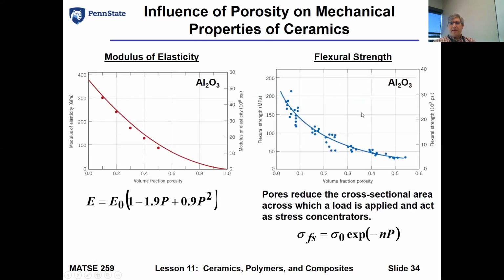So that leads us back into why do they fail? This flexural strength is going to vary, and it goes back to that processing. We talked about process structure properties a lot leading up to this throughout the course. But in this case, the process structure properties really come back to porosity and these pores. What they do is they reduce that cross-sectional area. They lead to stress risers.